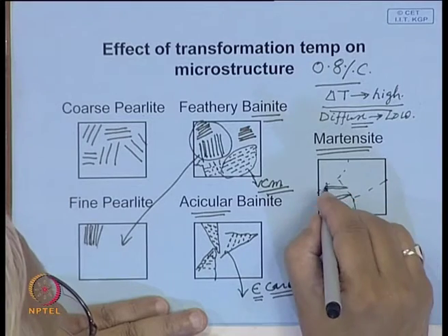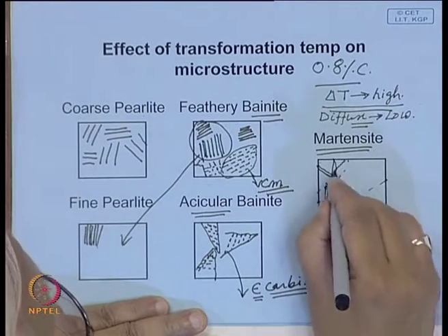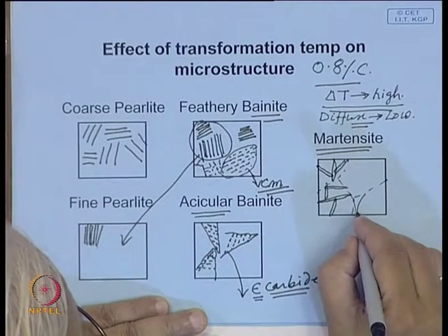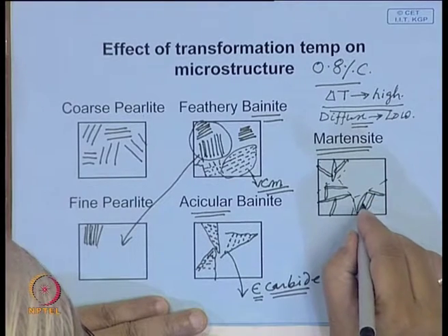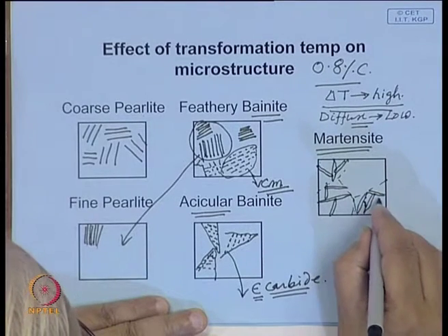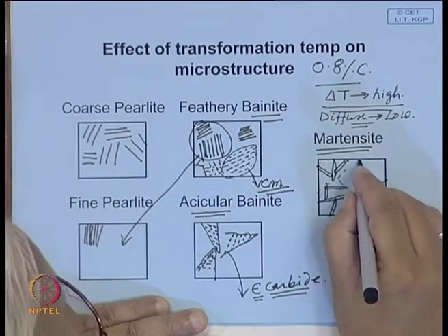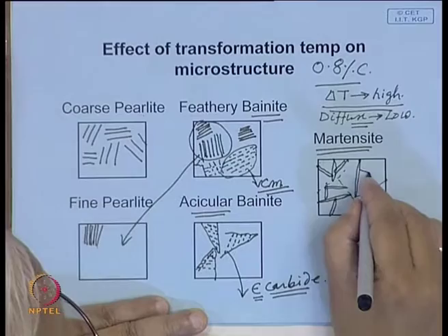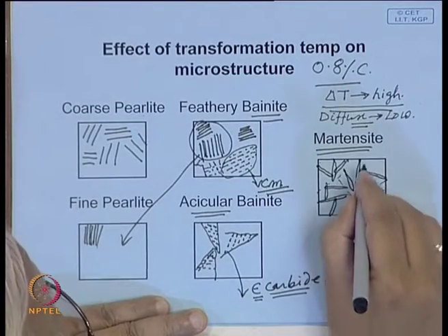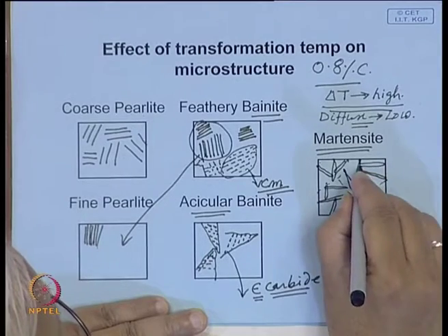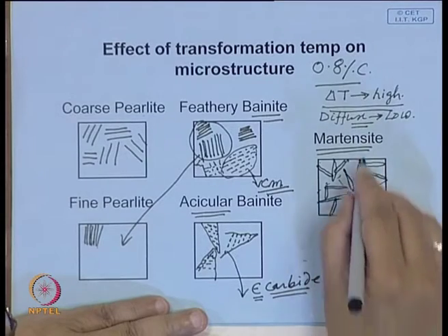an entire thing. They cannot cross the grain boundary, but this entire thing is a single phase structure. Their fineness will also depend on how large the austenite grain is. If the grains are coarser, you can even see these needle-like structures in an optical microscope, and this type of structure is called martensite.